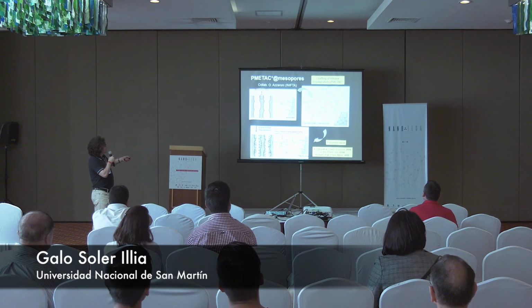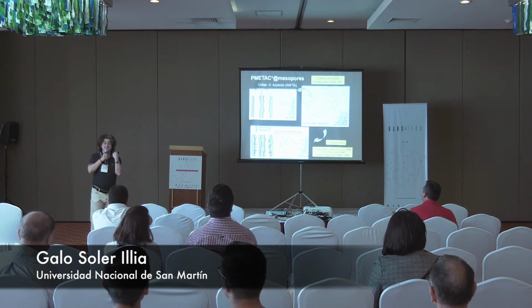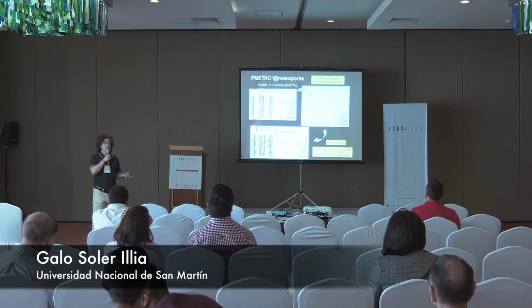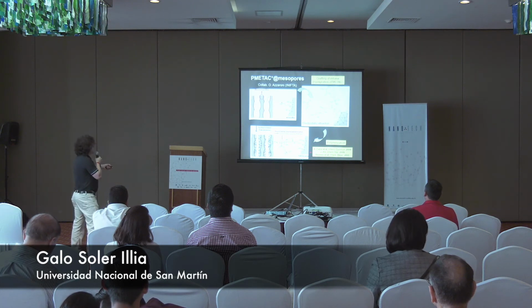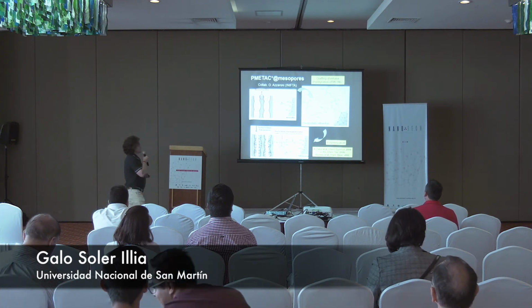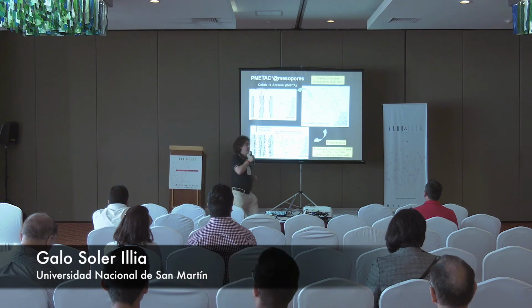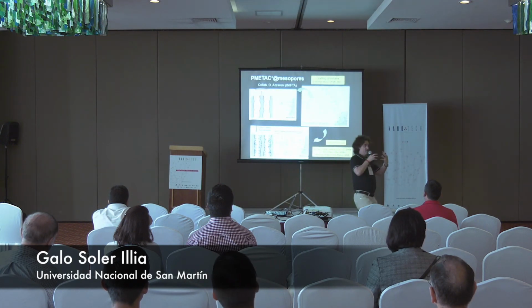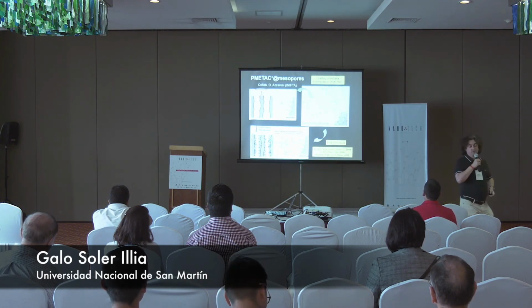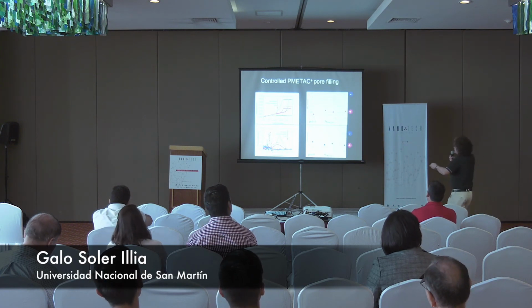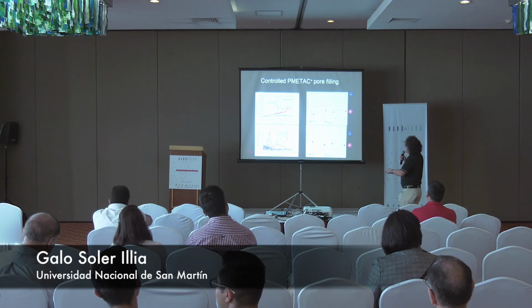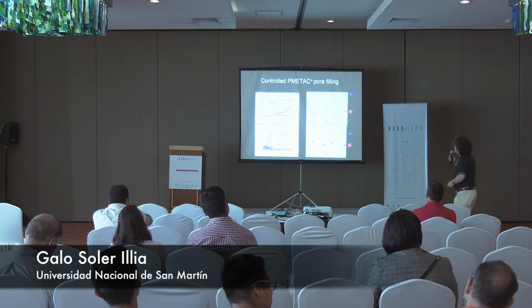And we can take advantage of the fact that we have a negatively charged surface to attract positively charged monomers. Then we make a 1,000-fold pre-concentration, and we polymerize inside the pores. We have a positively charged polymer inside the pores. We recorded this, we saw that we lost porosity, we changed the pore size, everything was good.